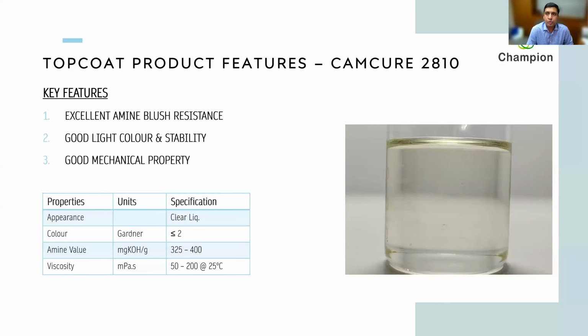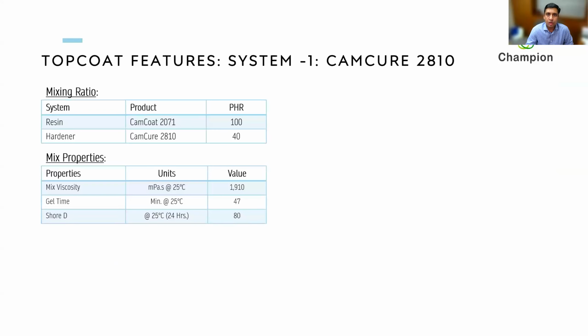When we talk about CamCure 2810, as you can see from the image, it's a very, very light, pale yellow curing agent. It gives excellent amine blush resistance. It's a very light color and has great color stability, and it also gives very good mechanical properties. I'll talk about the details of this system. As you can see, the mix ratio is very convenient with CamCoat 2071. It's a 100:40 parts mix ratio.